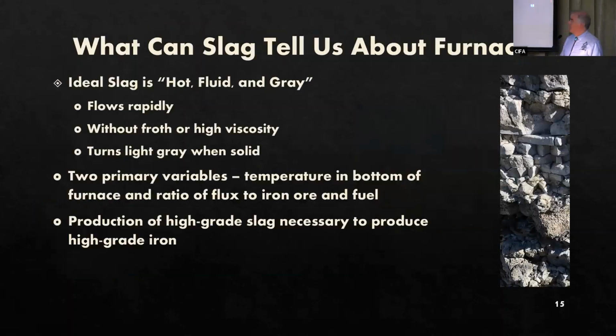So with that background, what can slag tell us about how the furnaces were operated? And why is slag so important? Well, for centuries, workers at hot blast iron furnaces described ideal slag as hot, fluid, and gray. In other words, when the slag was tapped from the furnace, ideal slag flowed rapidly out of the furnace without froth or high viscosity and turned light gray when it solidified.